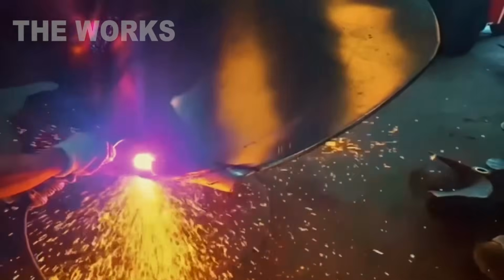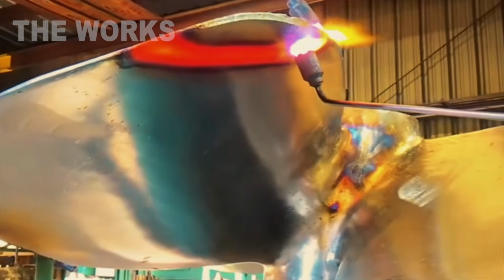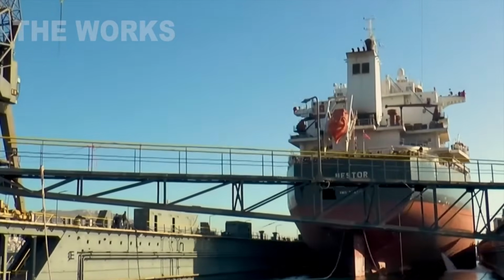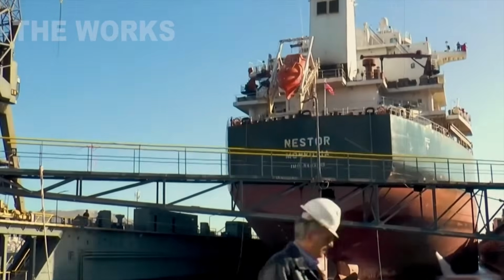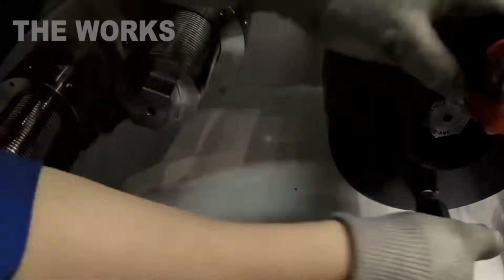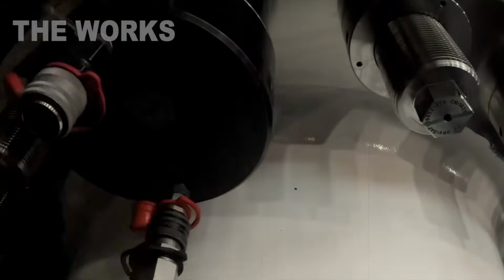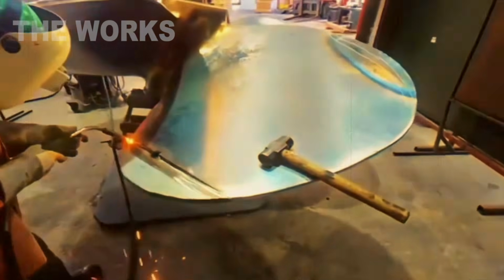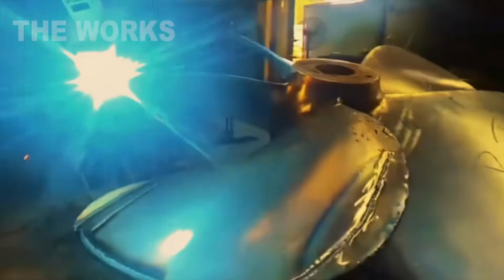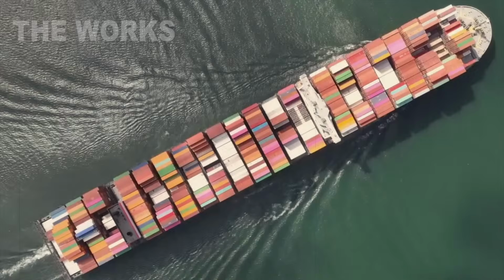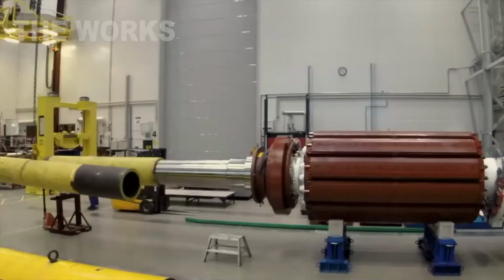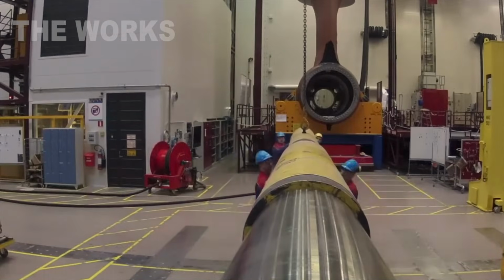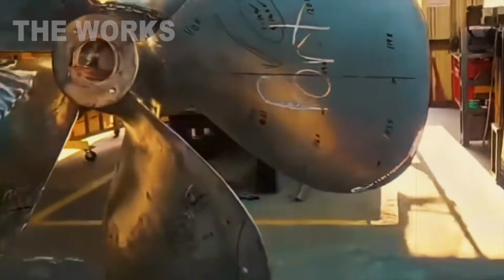What remains is a cavity shaped like the propeller, a negative. They coat the interior surface of the mold with a refractory compound, so the molten metal won't damage the sand. Then they bolt both halves back together. The mold has to withstand the pressure of 130 tons of liquid metal. They install the gating system, channels that'll feed metal into the mold. It's calculated so the fill happens evenly, without air pockets or cold joints. The mold is ready. Now comes the really impressive part, melting the metal.